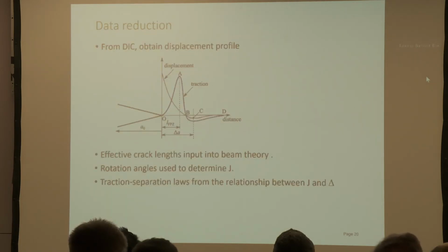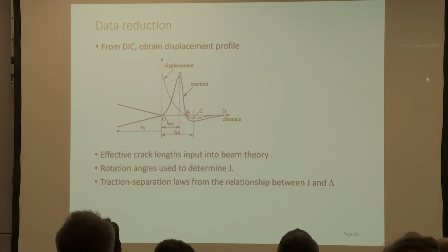So there are techniques where we can measure the displacements, and these displacements can be measured both behind and in front of the crack tip, and also the rotation angles. And this is a powerful approach because we can then achieve several things simultaneously. So one of the things that we looked at was, in fact, looking at, from the DIC data, the displacement profiles ahead of the crack tip. And this enables us to do this with quite a high degree of accuracy using DIC.